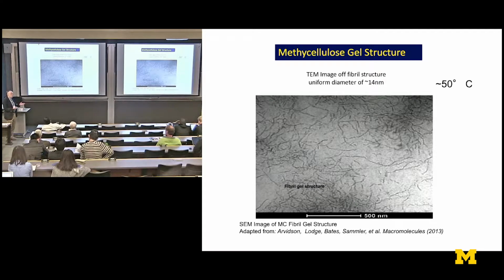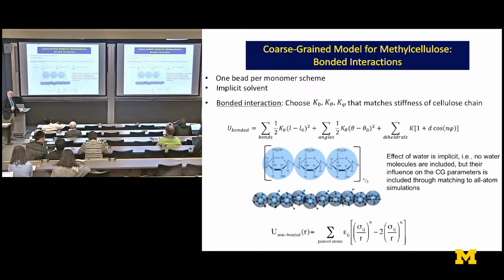So we don't have a hope of using atomistic MD to predict the kinds of structures that are formed. So we have to coarse grain. We do that in a systematic way by coarse graining each monomer into a single bead. But because the interactions of this monomer depend on its substitution pattern, for each substitution pattern we need a different bead and different bead parameters, the size and the interaction. So we have to get these coarse grain parameters somehow.